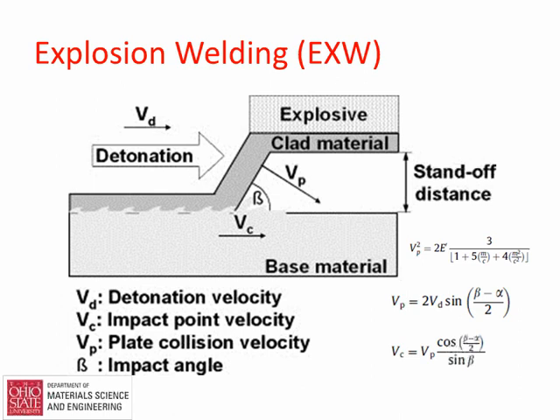Okay, so the first type of collision welding, and the most popular one, I think most of you here would have heard of this, is explosive welding. This was discovered quite a while ago, but it started being applied in the 60s and the 70s. This basically has a target plate, the explosive above a clad material or the flyer plate, and as the detonation wave passes through the explosive from one end, the flyer is driven to the base, and the waves are formed. And this is the basic process that a lot of the theory of collision welding is based upon.